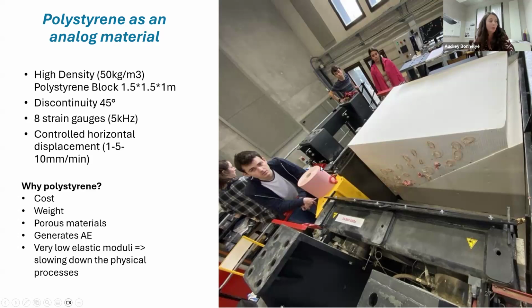And we've been doing some experiments by controlling the horizontal displacement. So from one side, just to make one part of the polystyrene go up over the other, and to have a look at the friction on that interface. So why polystyrene? Well, first of all, because it's cheap. I wouldn't say really cheap, but it's one cheap way to do it. Also because of the weight, because those blocks are huge, and despite the fact that we have a crane to carry everything, in our case the blocks are too big, so it's not that easy to use the crane to put everything inside of the vessel. So it means that we can carry it by hand to put it in the vessel.